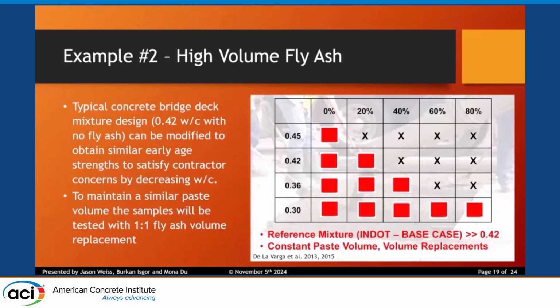The second example I'll talk about here is high volume fly ash mixtures. Now, these were set up to be similar to a bridge deck mix. So the original baseline case is a 0.42, right? And we're looking at trying to do this. The whole idea here is I can take advantage of that gel to space ratio concept, and I can reduce the water to cement ratio to get that certain strength at a particular early age.